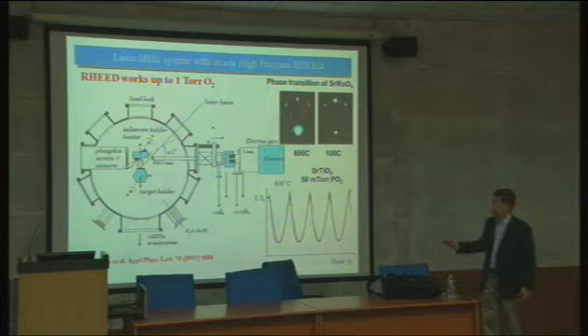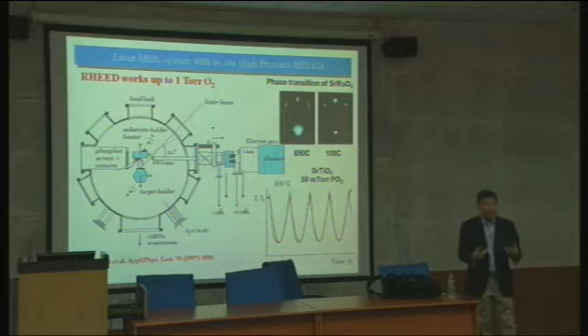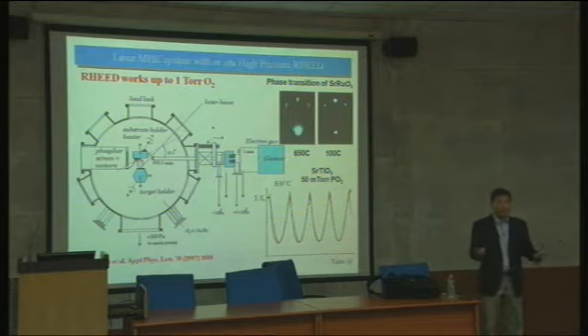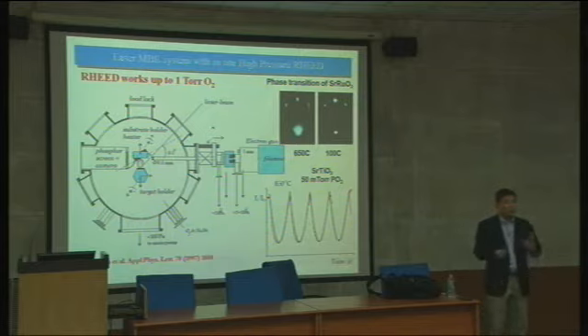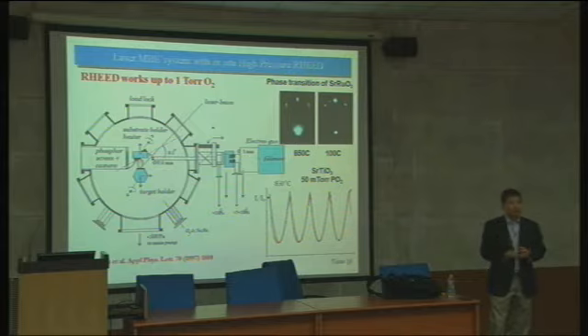So that means the electron beam travels from here to the exit of the beam inside the good vacuum. So the mean free path is very long, and you can travel without scattering. You can exit here, then this one's very close, and you can see that. So that's one very important step to make this atomic layer control in situ monitoring possible.